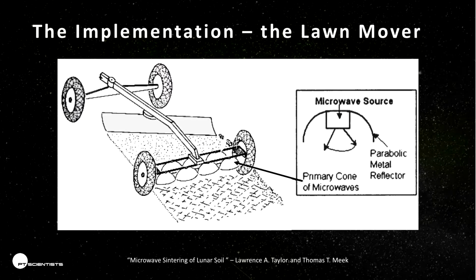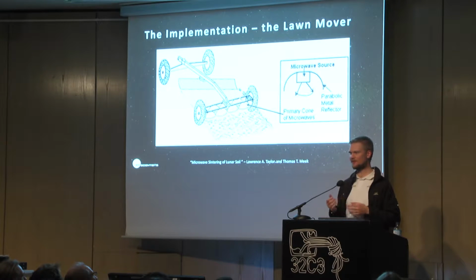If you have a microwave, you can make a surface coating of the regolith. When the Apollo astronauts were coming back into their capsule, they had the problem that the regolith is so fine that it actually went through their spacesuits, and they got black fingers. So the idea is that when you create a surface coating by microwaving the surface, you have a solid thing you can drive on, where you don't generate as much dust when you're landing or driving on it. And thus, if you want to build a lunar base and you have to go out often, not dealing with as much regolith is a very nice property to have.